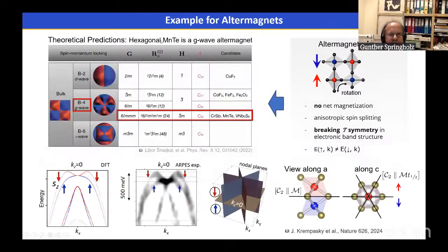On this slide, we have studied in more detail manganese telluride, which is listed in this table, published in this Physical Review X paper of Libor Šmejkal and collaborators. So for these altermagnets, the system has to show particular symmetries. And here on the right-hand side, there are some candidate materials listed, which fall into the different classes. For example, in this class, which are called g-wave altermagnets, there are materials such as chromium antimonide, manganese telluride, and other materials. There's also ruthenium oxide, which is also an altermagnet with a Néel temperature above room temperature. Manganese telluride itself has a Néel temperature of around 310 Kelvin.